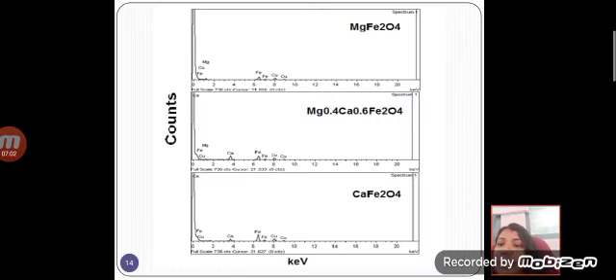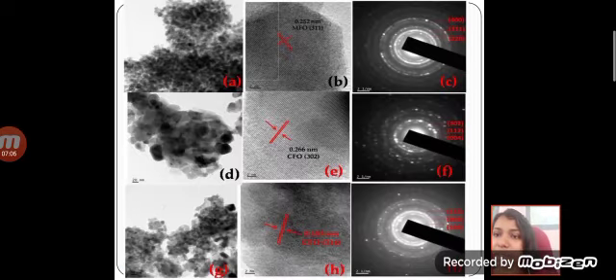Then these are the TEM images. We can see the TEM image of the magnesium ferrite, and then the HRTEM image and the SAD pattern of the magnesium ferrite, and D, E and F are the TEM, HRTEM and SAD patterns of Mg0.4 calcium, the sample with 60% calcium. And in the last figure, G, H, I are the TEM, HRTEM and SAD patterns of calcium ferrite samples. We can see that the samples show a spherical morphology, and the lattice d-spacing is calculated from the HRTEM, which is also indicative of the crystallinity of the samples. The SAD patterns also show the crystallinity and the structural transformation.